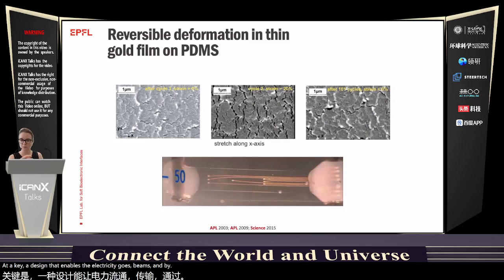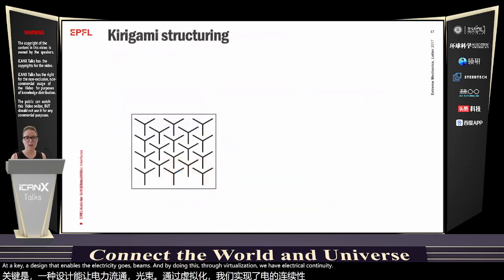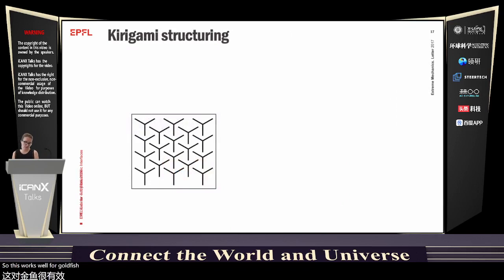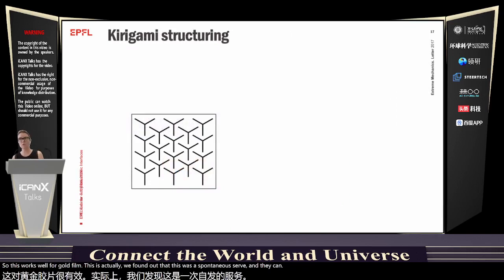And by doing this through percolation, we have electrical continuity. So this works well for gold film. We found out that this was a spontaneous growth mechanism for the gold films onto our elastomer.